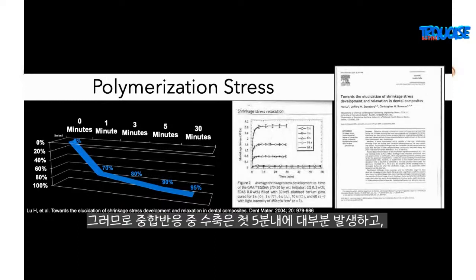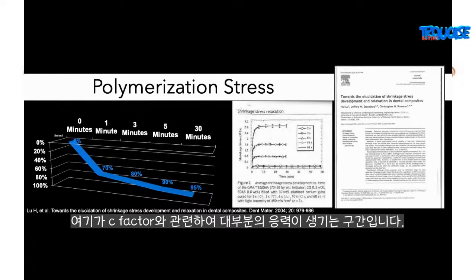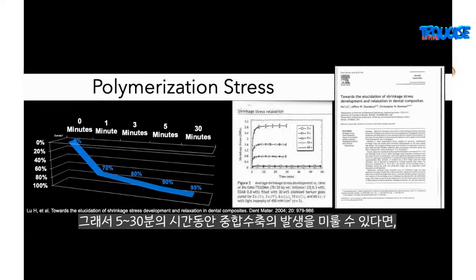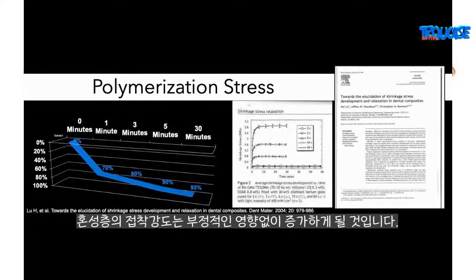And so in a polymerization reaction, the shrinkage happens mostly in the first 5 minutes. And that's where most of the stress will come in C-factor configurations. So the polymerization stress, if we can delay it to the 5 to 30 minute time frame, then the hybrid layer is not negatively affected in its developing strength.